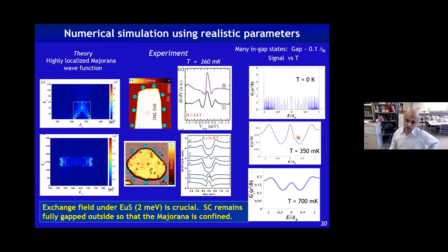And in the case of the simulation, they find that although our measurements are around 360 millikelvin measured temperature, then the peak is well defined. Whereas what we see is something closer to this. In other words, we have thermal broadening or even instrumental broadening. Our resolution is not very good. So the measurement, the filtering system and all that, we have to improve the electronic noise in the system.